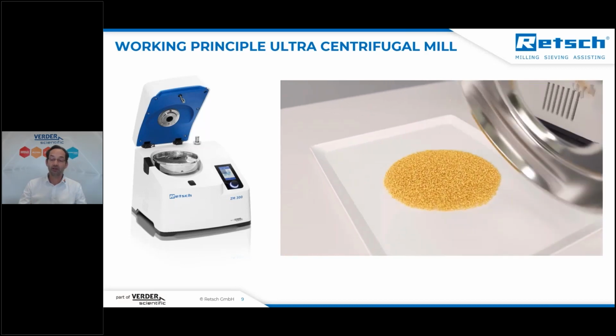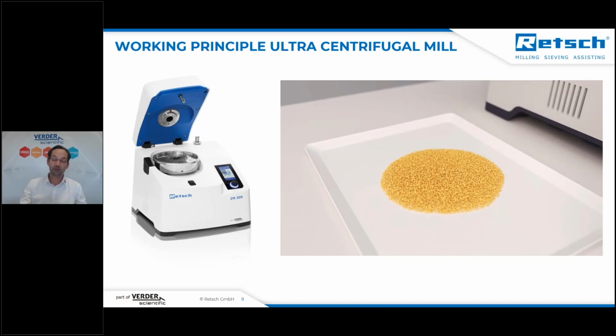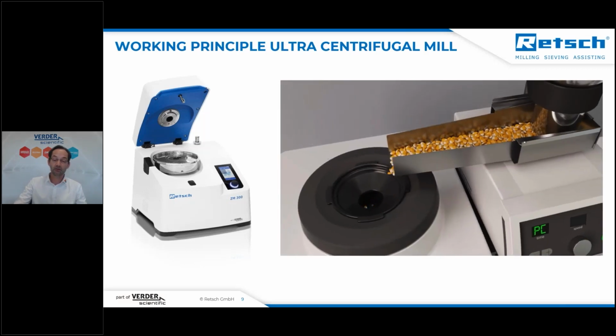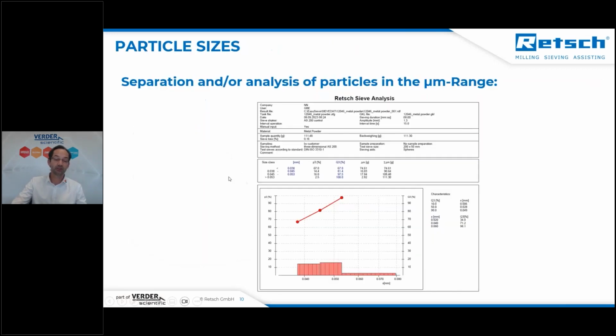But as I mentioned before, for the resin, for example, we've used a sieve of 0.12 millimeters, and we were able to grind 60–70% below 50 micrometers. But as said, we need all of the material to be fine enough to avoid clogging of the 3D printing nozzles. So sometimes it's necessary to remove oversized particles. And this can easily be done with a sieve shaker.